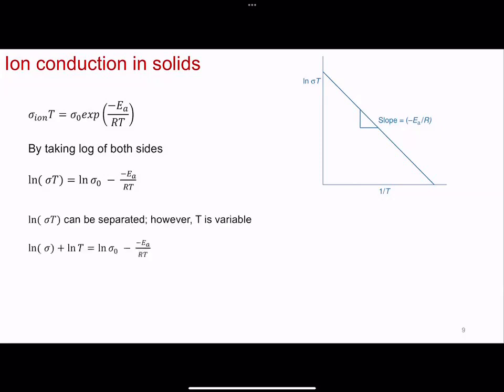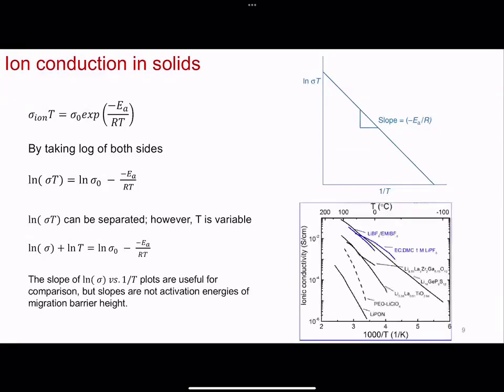Now, what you've also probably seen is the natural log of sigma versus inverse T. You can mathematically separate them, right? ln of sigma T, you can separate into ln of sigma plus ln of T. It's all true, but T is variable, right? So while you cannot get the activation energy from plotting ln of sigma versus inverse temperature, it is a useful way of presenting data if you have a lot of different materials that you want to overlay on a plot. You want to see the sigmas relative to each other. It's a very useful way of communicating that information. But you can't just pick out the activation energy from the slope. But that's what you see.